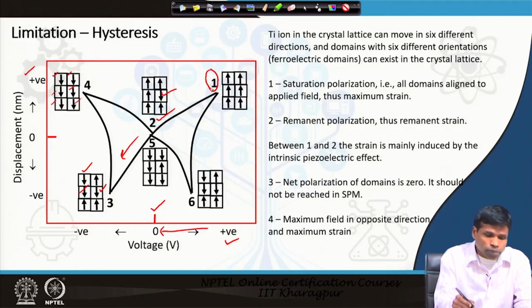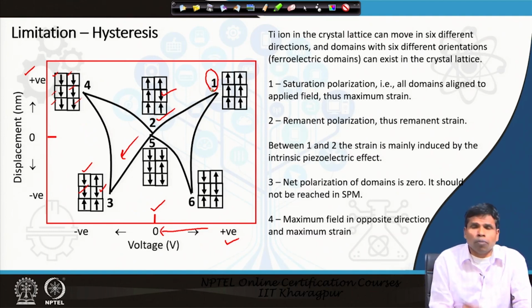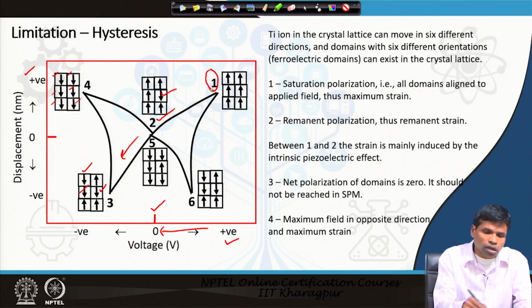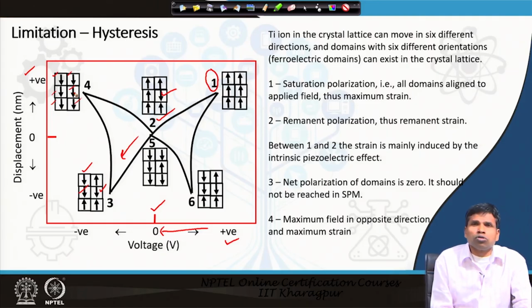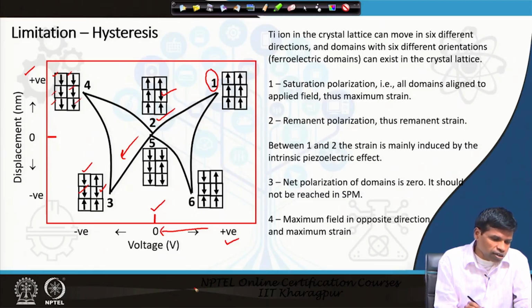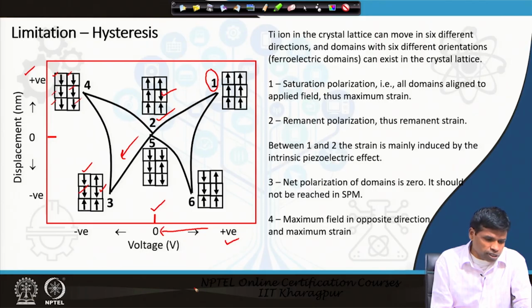So, what we see is that when these domains go from low energy states to high energy states, they have to overcome the energy barrier, and that depends on the history of the material system, and how that material underwent changes before we applied this particular voltage cycle. And due to this hysteresis, the extension of the piezoelectric scanner or piezoelectric element does not only depend on the applied field, but also on the history or the specific state of this domain structure.